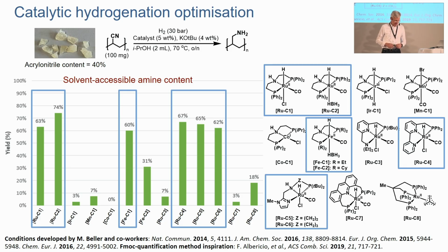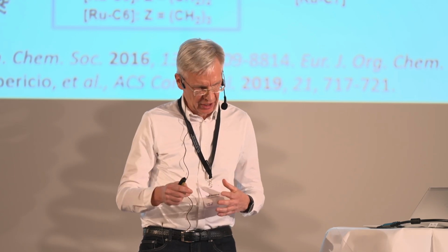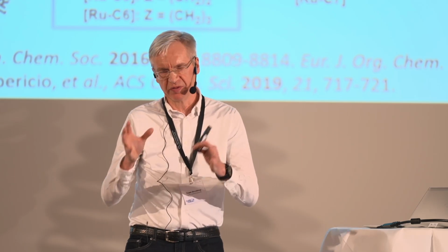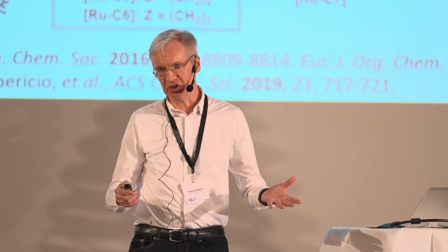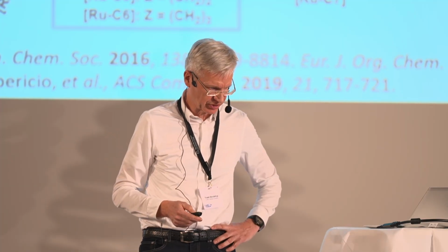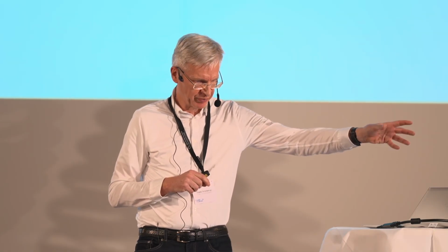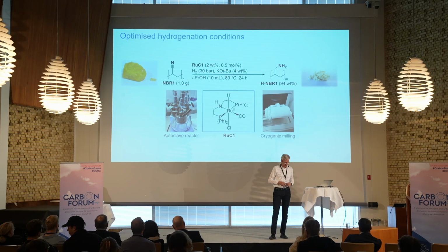And we screened a bunch of different catalysts and so on. The way we check that is we can do some chemical means by looking at what is accessible for the chemical reactions. This is the optimized process, where we take a nitrile butadiene rubber that we can buy, we convert it through reduction with a ruthenium catalyst, and then we cryo mill it simply to get uniform small particles. We do that to all the materials, because sometimes you end up with chunks. So we get them uniform so we have something to compare with.